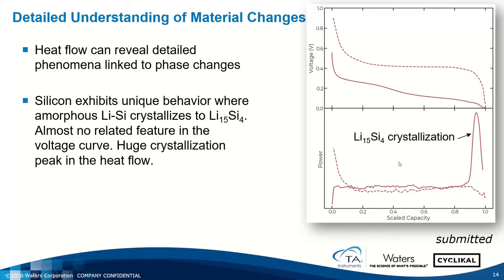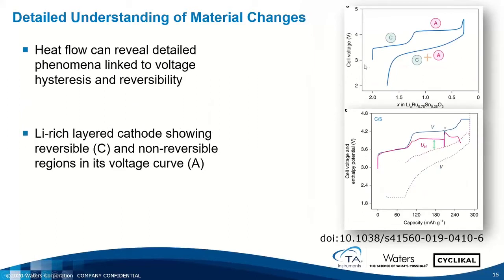So although it's barely noticeable in the coulometry, the current and voltage, you have this huge signature in the calorimetry. This type of thought process of looking at material phase changes can also be used to ask whether my material is reversible. In this paper, the authors used isothermal calorimetry to understand the changes in a material, and were able to identify that in this region of the voltage curve they had a reversible process that was basically intercalation, and here they had structural changes in their material. They could tell this by the changes in the potential versus the changes in the enthalpy potential.